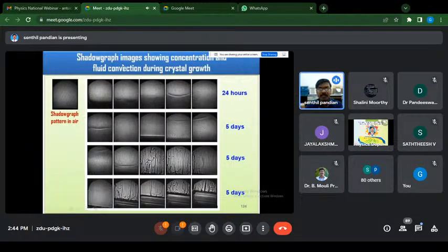So these are the schlieren images of the concentration field of this SR method grown benzamide crystal. You see the concentration at the bottom portion is higher compared to the top portion. This is for 1 day, and this is for the next 5 days, and the next 5 days, and the next 5 days. So totally 16 days. At this 6th day, you see the plumes start from the bottom of the glass ampoule. The plume is nothing but the movement of fluid flow from high concentration to low concentration.